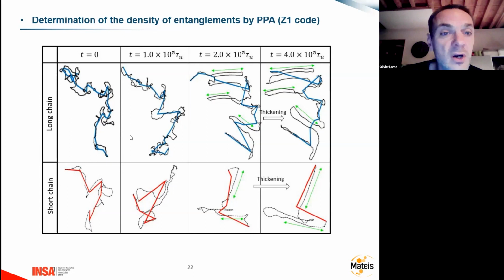And so here we have a PPA, primitive path algorithm, and the aim of this algorithm is to try to see the entanglement artificially. So for example, here in black, we have a given chain. What we do is we lock the chain ends and then we stretch the system just to get at the end some straight line. And here in blue, you have this primitive path, which shows that at the end of this stretching, you have some turns, and each turn corresponds to an entanglement.